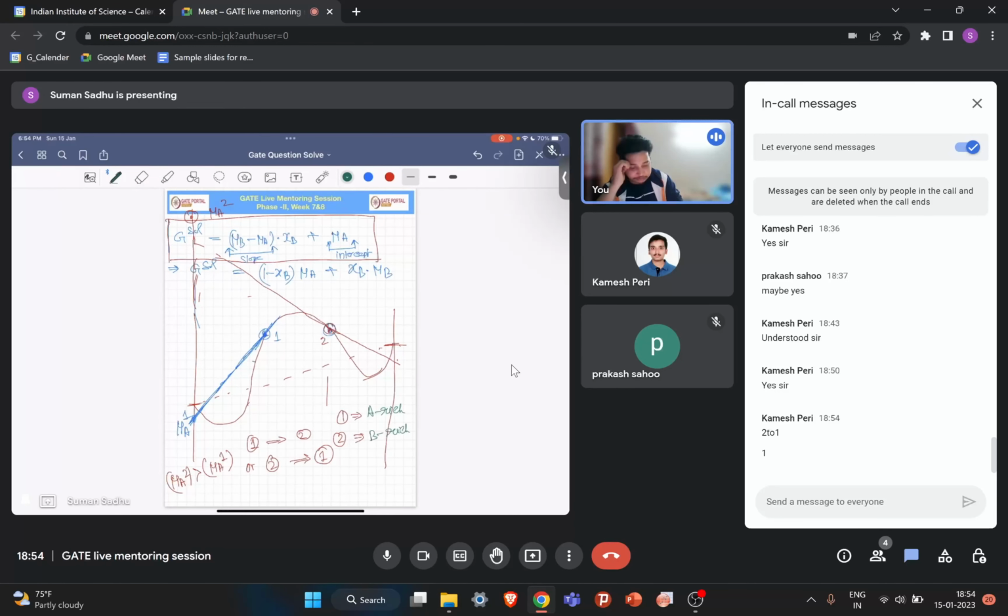In this kind of free energy versus composition diagram, that means when delta H mix is greater than 0, if you have any points inside the spinodal or inside the binodal points, A will move from the B rich side to the A rich side.